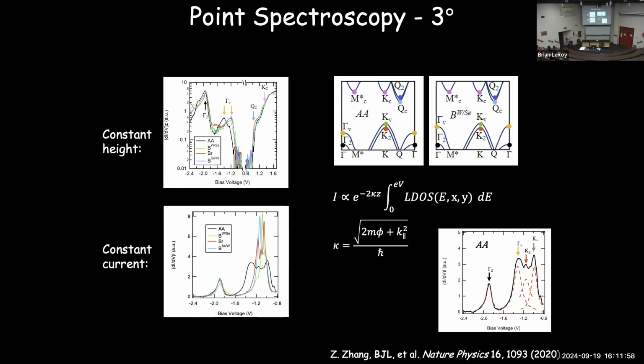So when we hit QC here, that state turns on. As we go a little higher, we hit the Kc, that point up there, and similar things over here in the valence band, the gamma point here, et cetera. This actually took quite a bit of modeling to work out what these points correspond to, because the simple picture of the density of states that I gave you before, e to the minus some value times z, is slightly more complicated, because this decay constant depends on the momentum that you're trying to probe. It's easier to probe states which have zero momentum here on the left-hand side. States out at finite momentum decay more rapidly and are more difficult for us to probe.